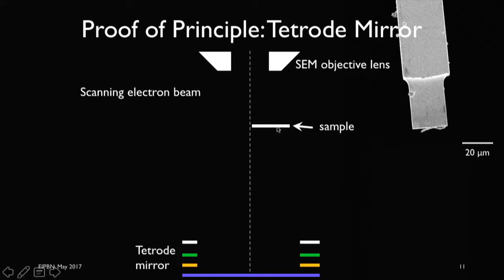First, we placed the sample very close to the optical axis of the objective lens, and also placed a tetrode mirror. I mentioned in the beginning, a tetrode mirror is the kind of mirror that gives us better control over the divergence angle of the reflected beam. And we placed this tetrode mirror, plus lens, I should say, such that its optical axis overlaps with the optical axis of the objective lens. So you can imagine having this setup, when we start to scan the top surface of the sample, we would produce an image of the top surface. In this case, I'm showing it on the right side here. That's just an image of a silicon cantilever that we were using as our sample. That image was produced by scanning the top surface of the sample.